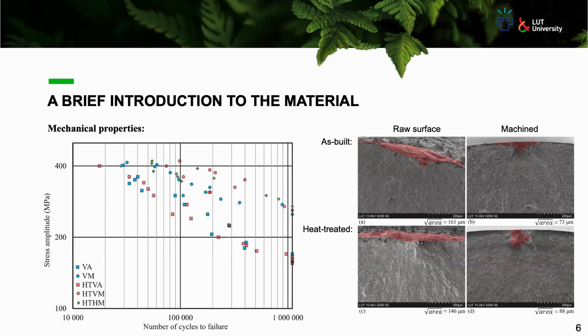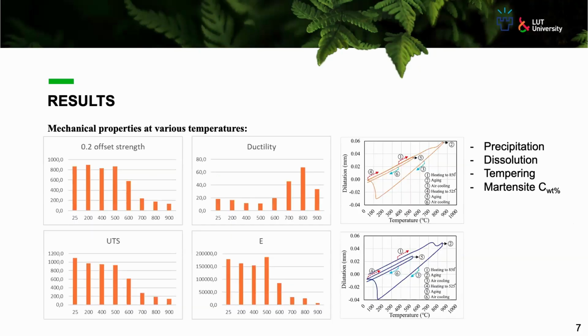So if you test CX after heat treatment, MS1, or even in some cases 718, and you don't see any kind of improvement in the fatigue performance, don't be surprised. This can happen. You can even see the failure initiation sites in the as-built and heat-treated versions are similar. The size of the defects and their presence are similar to each other.